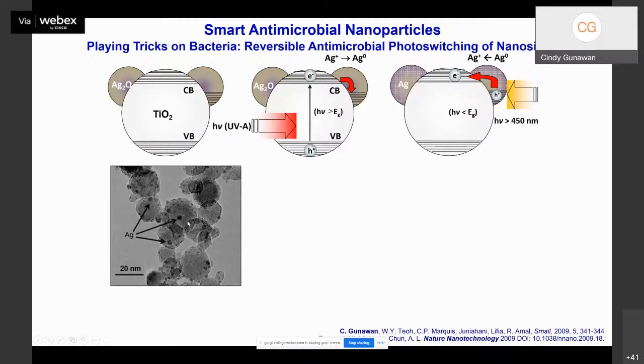So you might be wondering, why titanium dioxide? Because we know that titanium dioxide is a semiconductor. It means that it is responsive to UV light. So upon irradiation of this particle composite with UVA, because of the band gap of the titanium dioxide, there will be an excitation of electrons from the valence band to the conduction band of titanium dioxide. And in turn, these electrons will reduce the Ag+ deposits on the surface of titanium dioxide to metallic silver.